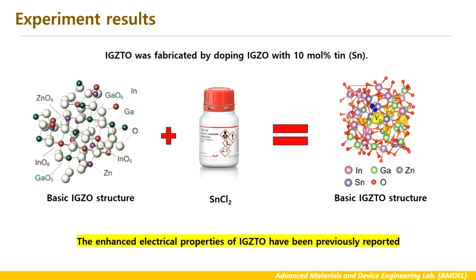We began with a basic IGZO structure, which is widely used in oxide TFT research. To further improve electrical properties, we fabricated IGZTO by doping IGZO with 10 mol% of tin. Previous reports suggested that tin doping can enhance conductivity and stability, so we used this as a foundation.